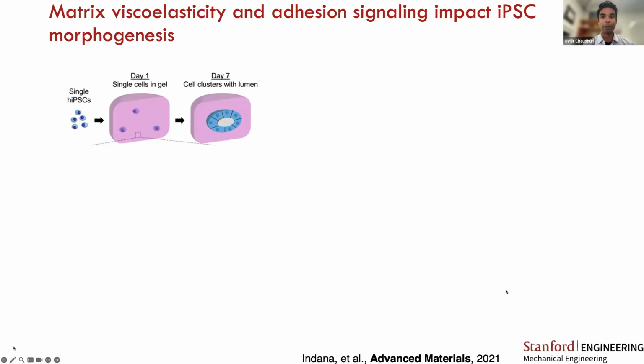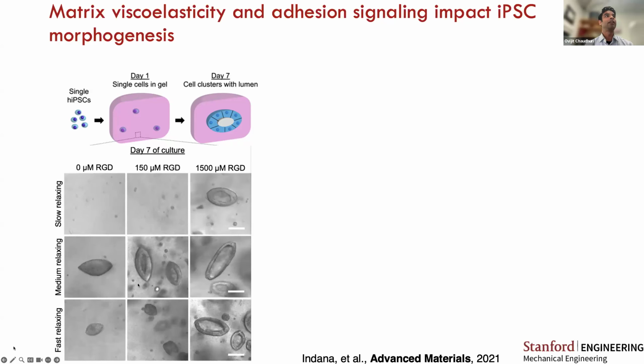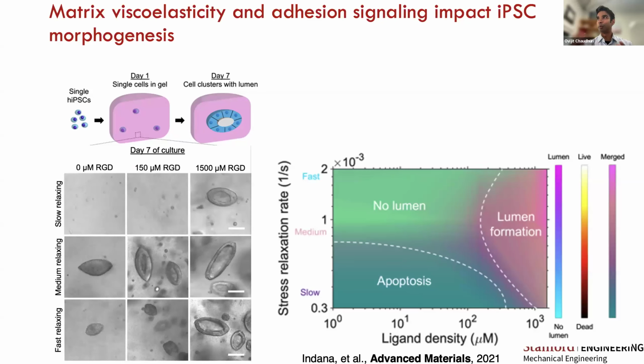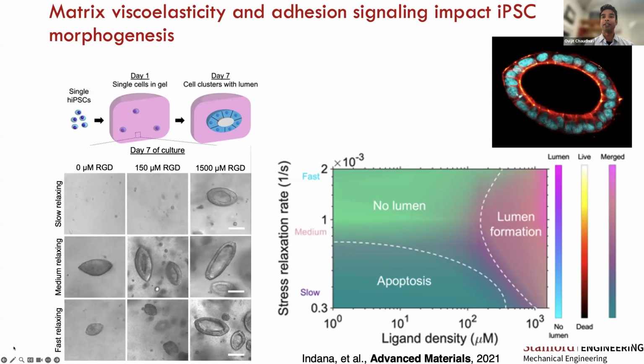Okay, so what we first did was culture human-induced pluripotent stem cells in hydrogels with a range of viscoelasticity, stiffness, and RGD ligand density. And we immediately see from bright field images that after 7 days, we see some striking differences in the morphology of these iPSC clusters that form. And we can put together a phase diagram where we see that in slower relaxing matrices with lower ligand densities, the cells primarily undergo apoptosis, whereas at higher ligand densities and with faster relaxation, the clusters are able to form a lumen, as shown in this nice immunohistochemical image on the top right here.